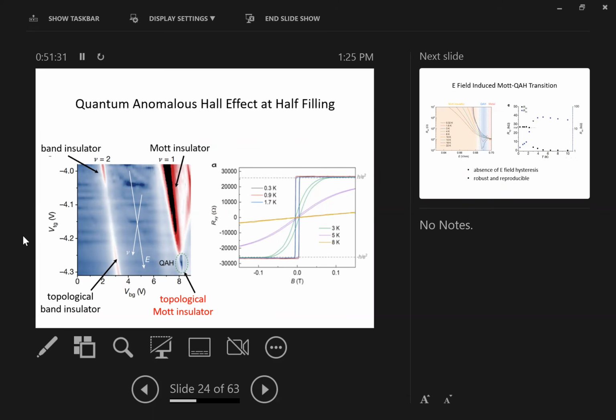Now the focus of this talk is about filling factor 1, half band filling. Here at a large band offset, when charges are all in one layer, this insulating state is just a Mott insulator. But as you increase electric field, when the charge starts to occupy the other layer, very surprisingly, unexpectedly, experiments discover a spontaneous Hall effect. Even at zero external magnetic field, you see the Hall effect appears, and at low temperature this Hall effect becomes quantized, approaching h over e squared. This is the so-called quantum anomalous Hall effect. Quite surprising. So this leads us to speculate that you start from a Mott insulator and you tune it into a topological regime. So maybe we can call that a topological Mott insulator, whatever it means.